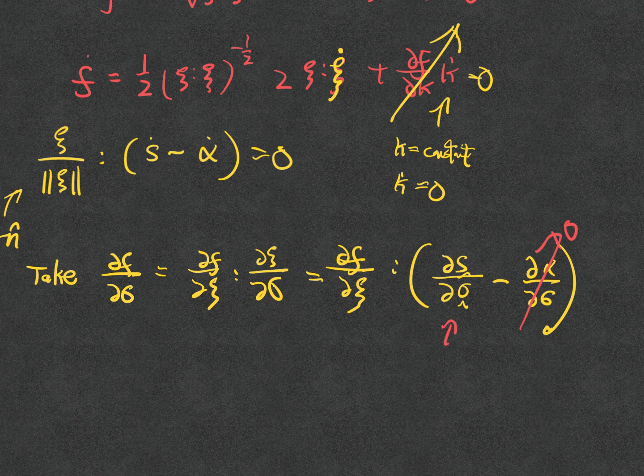This part, if we recall from what we did before, we made the derivation before, and if this one is the plastic flow direction, then this whole term, the stress gradient, is equal to n double dot I, the fourth order identity tensor, minus 1/3 of the second order identity tensor times I itself, and this is a fourth order tensor.